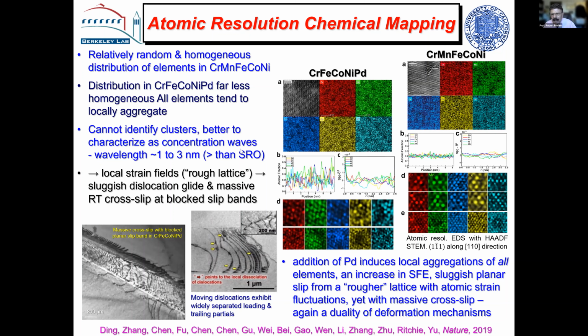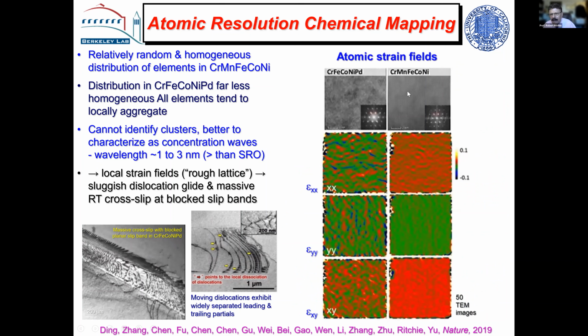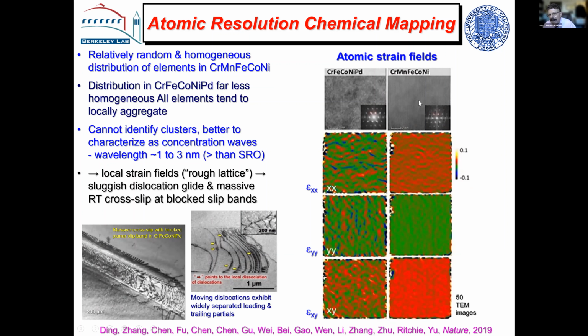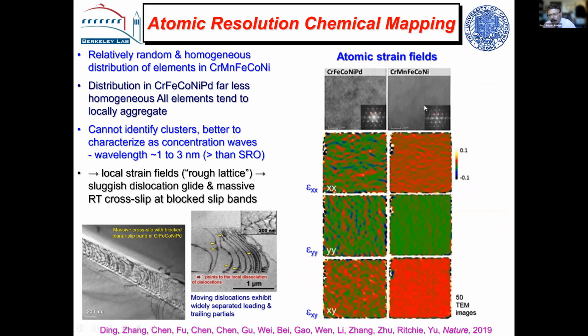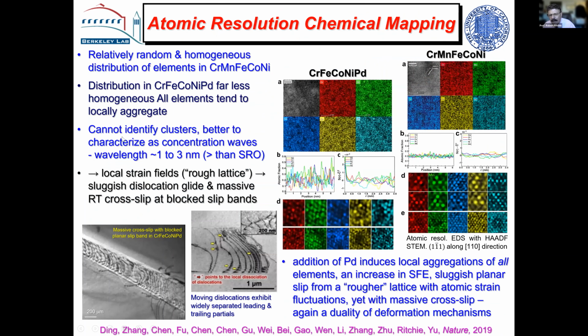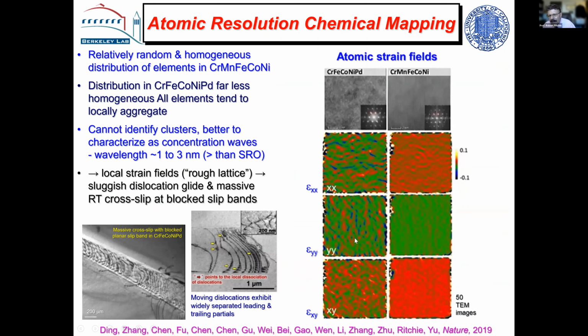And if we can measure the atomic strain fields in these conditions, this is basically looking at the shear strains and the tensile strains, and there's basically a key here in the control alloy where we don't see much in the way of these concentration waves. Then there's a small degree of positive and negative atomic strains. But in the one with palladium in, where we do see these concentration modulations over these 1 to 3 nanometers, then you can see quite a degree of positive and negative strains, which would roughen the lattice and act to possibly increase the strength of the material.